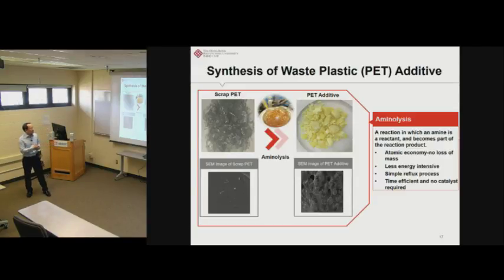And here's actually how the additive looks. It's in a semi-solid state at room temperature. But if we heat it to around 60 degrees C, it will become liquid. So at the mixing temperature for the asphalt mixture, this additive can be easily turned into liquid, and because it's a liquid, it allows us to very easily mix it with the asphalt binder. So the storage stability is not a problem at all for this additive, but it is a problem for the PET material.